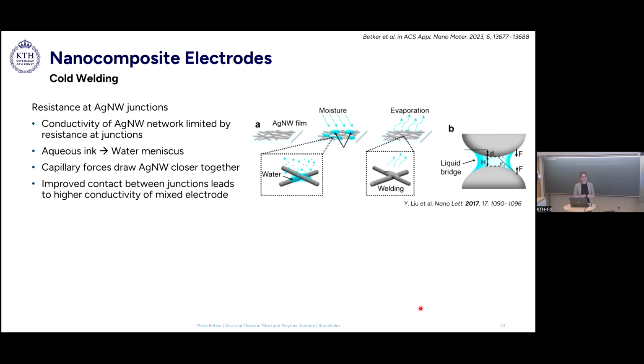It's called cold welding. So what they did here, they started with a silver nanowire network. And then they add moisture to the network. In our case, the moisture was already there because we had a water-based ink. Okay. And then when the water evaporates, this cold welding happens, which actually forces or draws the nanowires closer together, which enhances the conductivity drastically. And what is actually happening, you see in picture B here.